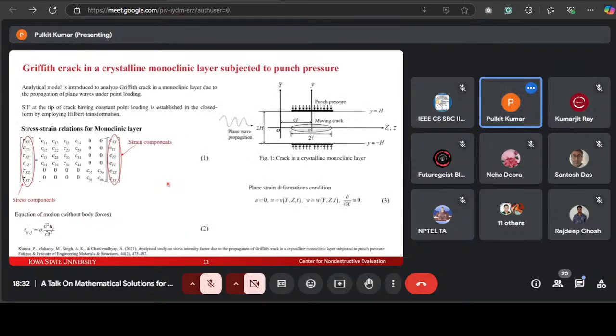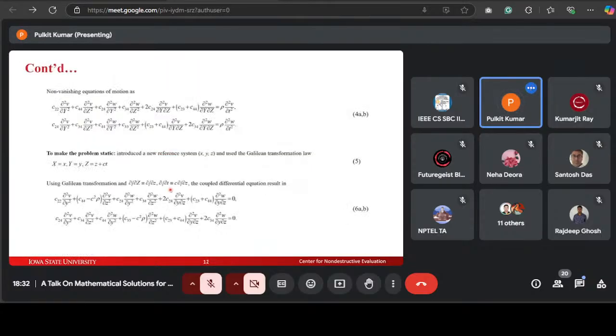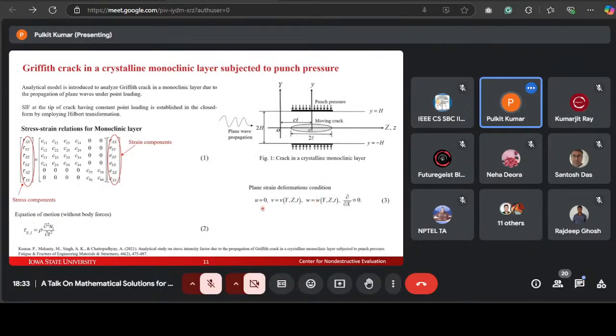The plane strain deformation condition for a moving crack because of the propagation of a plane wave in a crystalline monoclinic layer, which is parallel to the YZ plane, is defined by equation number 3. The question may come to mind: how are two displacement components possible? For pure plane waves in isotropic materials, one displacement component is sufficient. But if we are dealing with anisotropic media like monoclinic materials, two displacement components are possible. Here we are dealing with the two displacement components V and W. U, V, and W are the three displacement components in the direction of the X, Y, and Z axes.